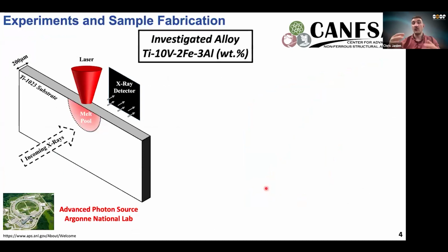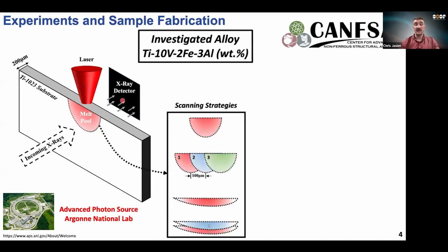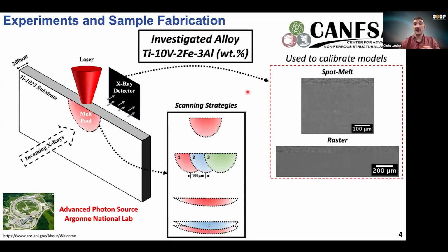Initially we wanted to understand what was going on in these materials at a smaller scale. To do this, we performed very specialized experiments at the Advanced Photon Source at Argonne National Lab, using the schematic experimental setup shown on the left here, where we are in one of the X-ray beam lines, and we bombard our material with incoming X-rays while we're melting and subsequently rapidly cooling or solidifying this Ti-1023 alloy. While the X-rays are incoming, they hit an X-ray detector in the back. We can use this to understand how the melting and solidifying responses occur in this material.